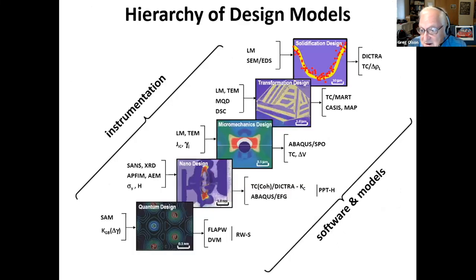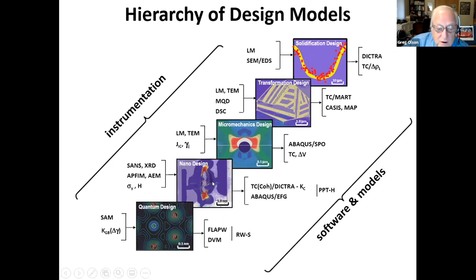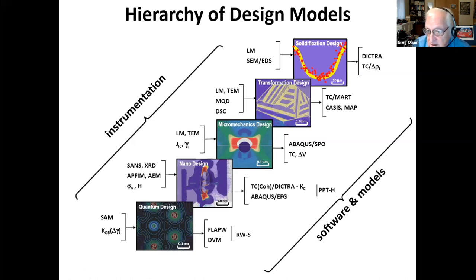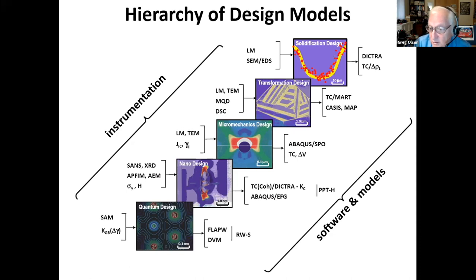The tools we ultimately brought together include DFT physics to predict thermodynamic properties — particularly valuable for surface thermodynamics, which is difficult to measure. The materials science tools have been most predictive and quantitative at the nanoscale precipitation and corresponding strengthening. For other mechanical properties, tools of micromechanics have allowed us to simulate unit processes of fracture and fatigue. It's really a combination of DFT physics, materials science, and continuum mechanics integrated together for performance-driven design, equally balanced with processability models of solid-solid and liquid-solid phase transformations.